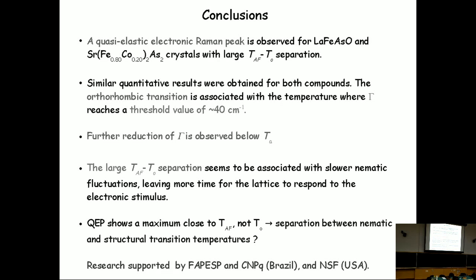And something that we don't understand yet, but it's a very interesting result, is that this quasi-elastic peak is a maximum close to the antiferromagnetic transition temperature, not the orthorhombic phase transition, meaning that apparently we have a separation between what we call the electronic nematic phase transition and the structural phase transition, at least for these two compounds that we have studied. That's a surprising result that we want to understand better. So thank you very much.